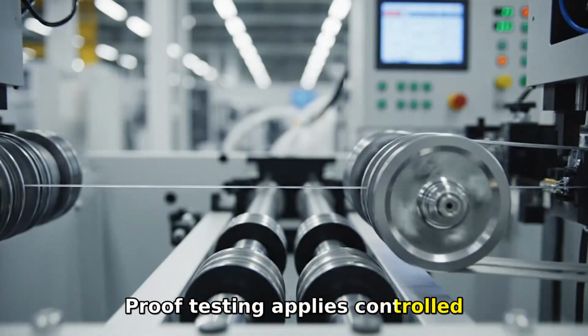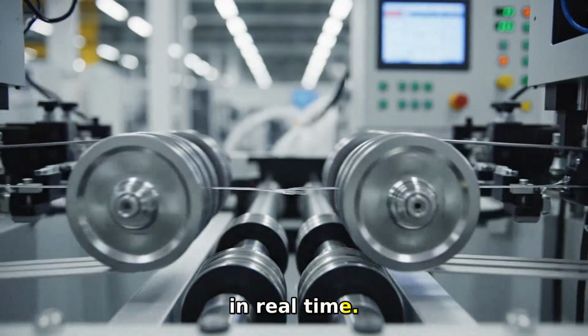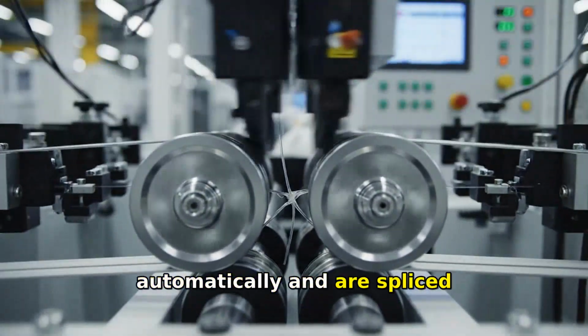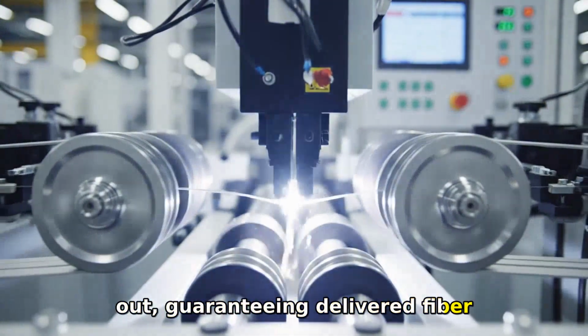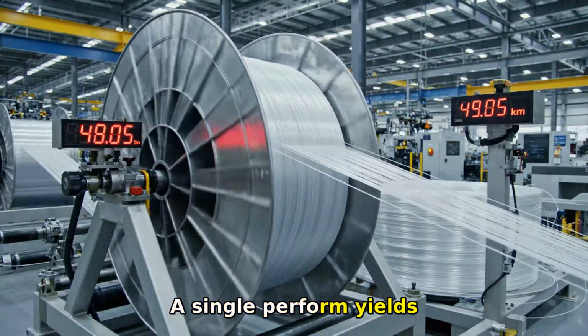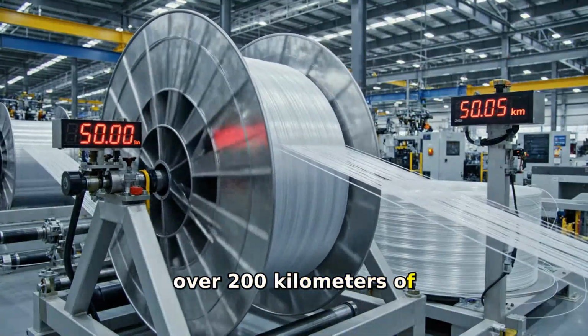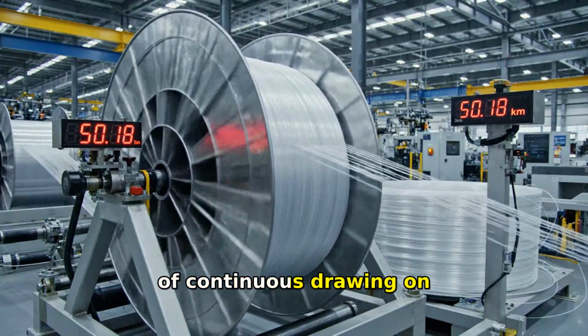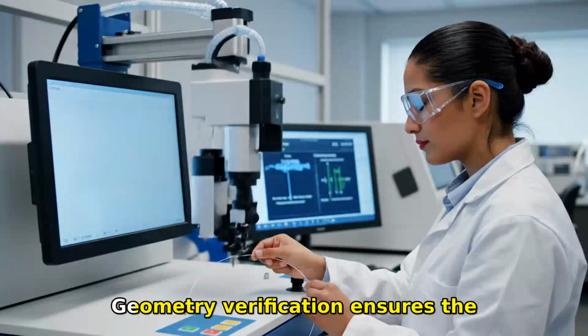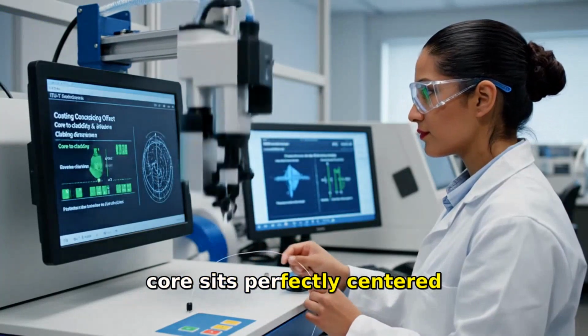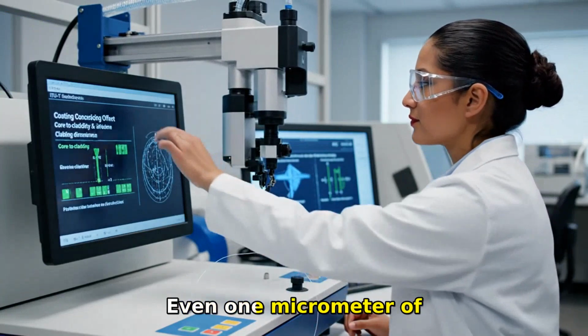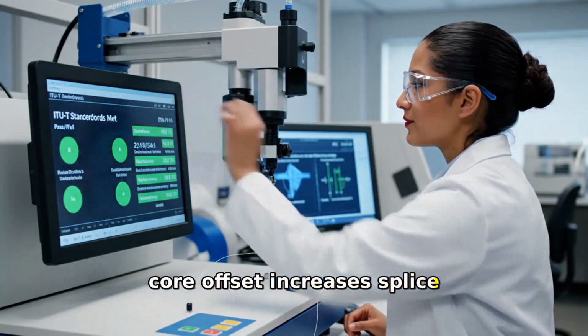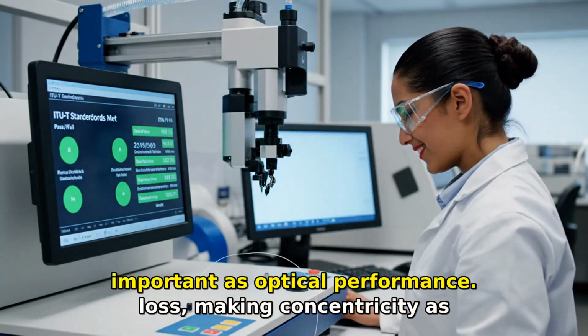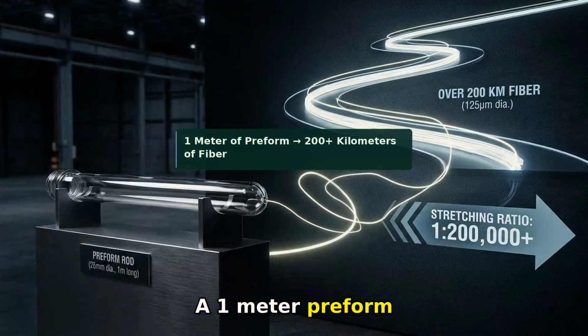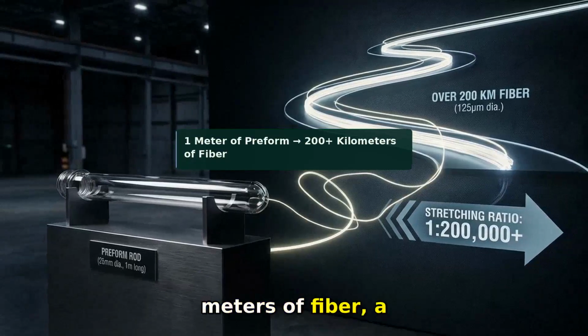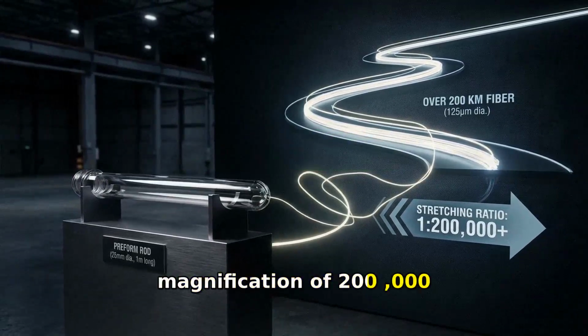Proof testing applies controlled tension to every meter in real time. Sections that fail break automatically and are spliced out, guaranteeing delivered fiber exceeds specification. A single preform yields over 200 kilometers of fiber, accumulated over hours of continuous drawing on precisely wound spools. Geometry verification ensures the core sits perfectly centered within the cladding. Even 1 micrometer of core offset increases splice loss, making concentricity as important as optical performance. A 1-meter preform becomes over 200,000 meters of fiber, a magnification of 200,000 to 1.